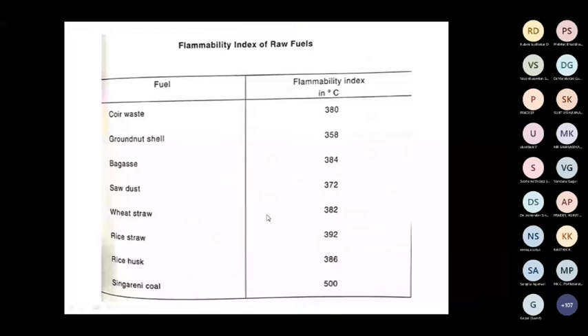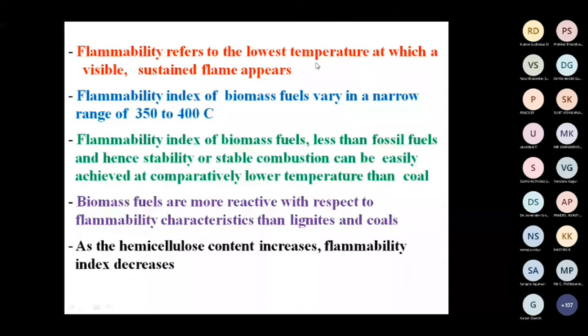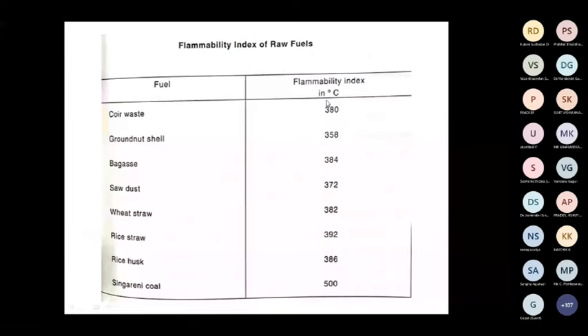So flammability refers to the lowest temperature at which a visible sustained flame appears. The flame appears here, that is called flammability. If we compare the flammability temperature for all the fuels, it varies from almost close to 350 degrees, 350 to 380 degrees. Coal we have 500 degrees. So from the flammability point of view, biomass fuels are better fuels, easily ignitable, for the obvious reason of high volatile matter content.